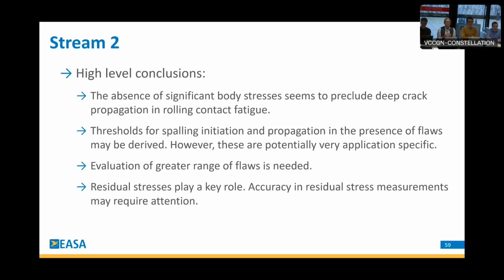It also seems possible, even though we realized we did not really have the time and capabilities to develop them, to develop a threshold for spalling initiation and propagation in the presence of flaws. However, it seems that this is very much application specific. So depending on many variables, one of them being the specific flaw for which you are trying to identify the threshold against. But it's clearly possible that when you appropriately replicate your design in a test specimen, you could ensure that you demonstrate that you are tolerant to certain kind of flaws developing into spalling.